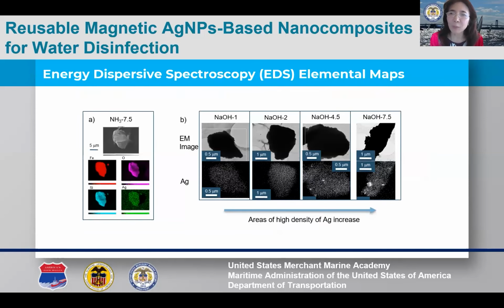Energy dispersive spectroscopy, or EDS, elemental maps of the nanocomposites confirmed the presence of all expected elements, iron, oxygen, silicon, and silver, which all shared the same spatial distributions. The fact that where silver was found, all other elements were present confirmed that silver nanoparticles were truly incorporated in the final products.